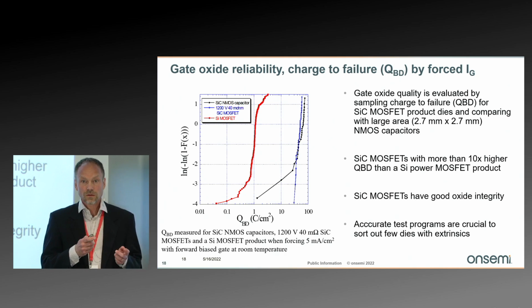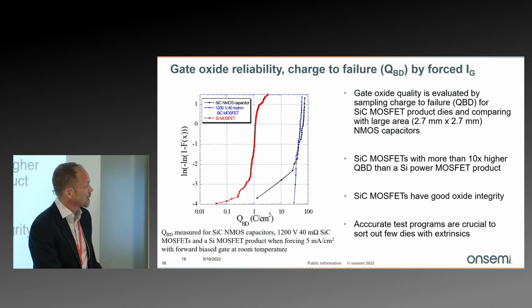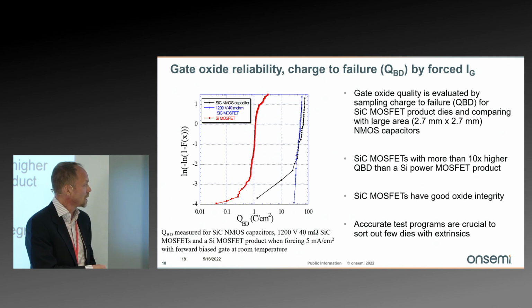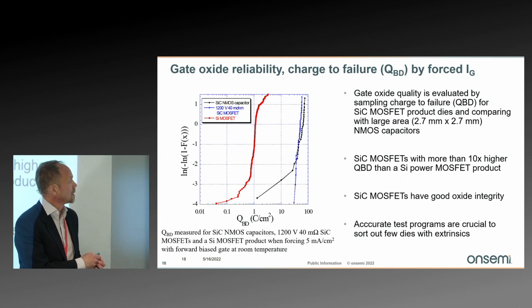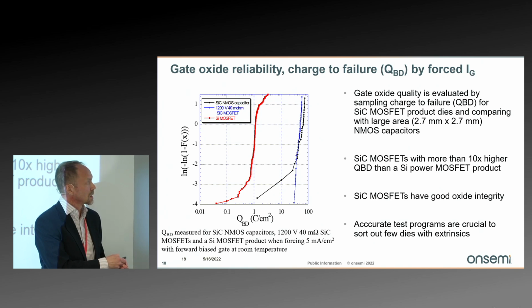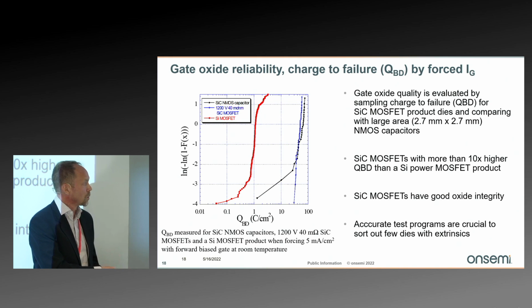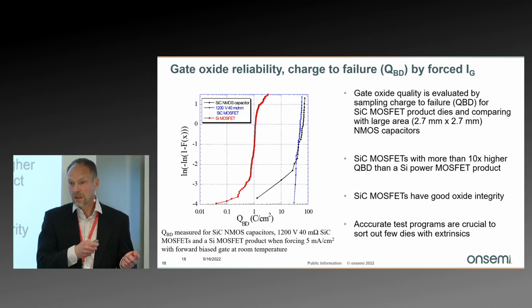And one easy way we have to evaluate gate oxide reliability or look for weak spots in a die, monitor quality, is to just force a current through the gate until we get a failure. We often use 5 milliamp per centimeter square, which is convenient. Then the gate oxide goes into breakdown, starts tunneling. We measure the charge until it fails. And here we can see results for NMOS capacitors compared with bin 1 product dies that pass the sort. We can see that the bin 1 product dies are as good or possibly even better than the MOS capacitors because we can sort out some areas with defects in the sort program.